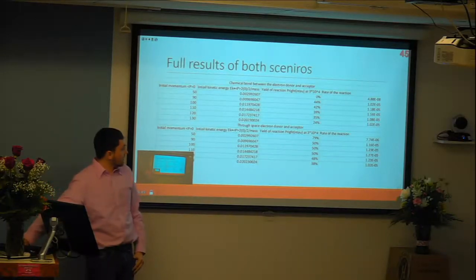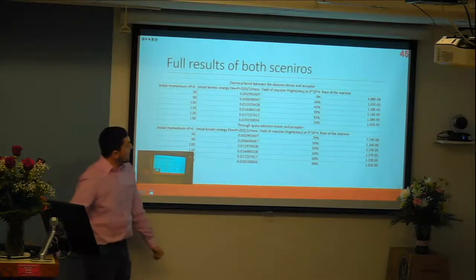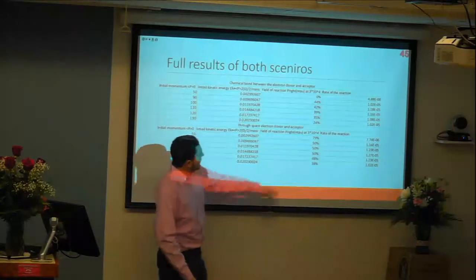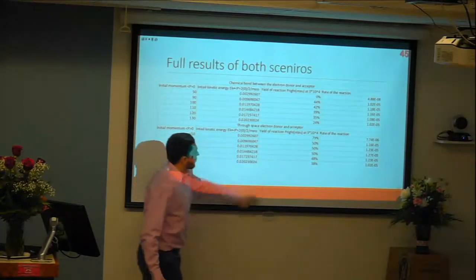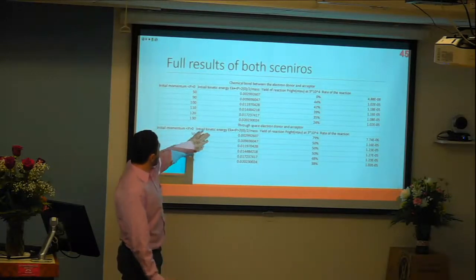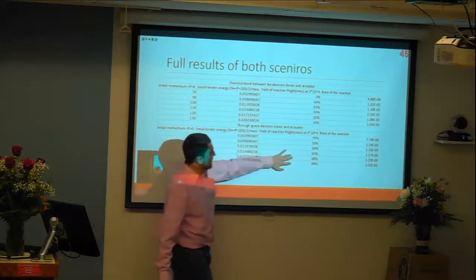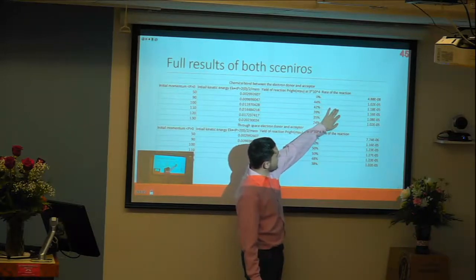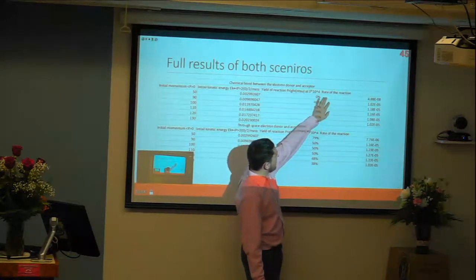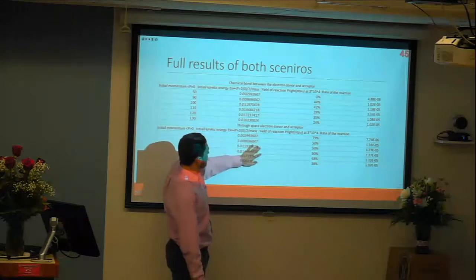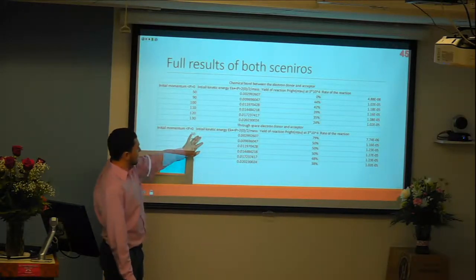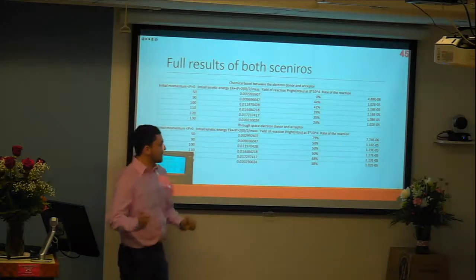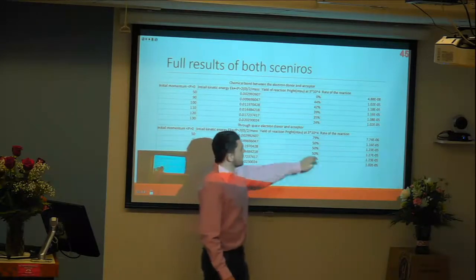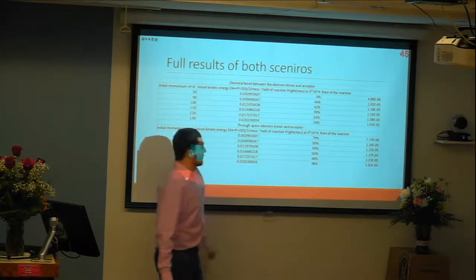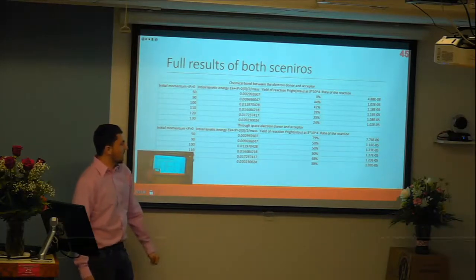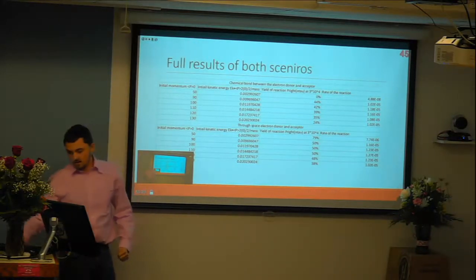Here's just a larger range of scenarios. In this, you will also see the rate of the reaction. And from what I see, this is the chemical bond, and this is the through space. And you see that the rate of the reaction at 50 does not achieve transfer, but in the through space, the momentum of 50 is enough to start transferring the electron over. It's also with a higher rate, but it decreases as you increase the momentum.